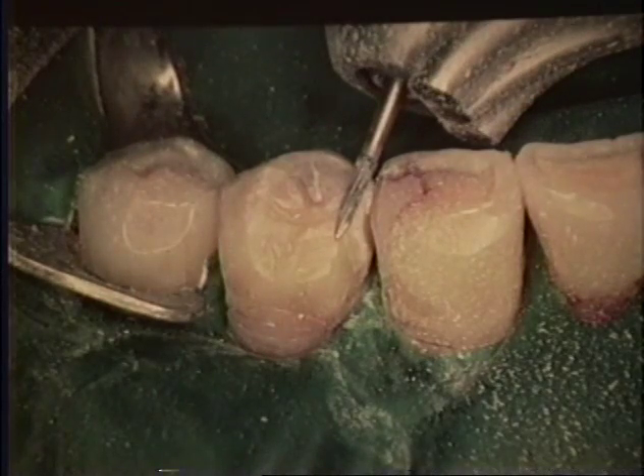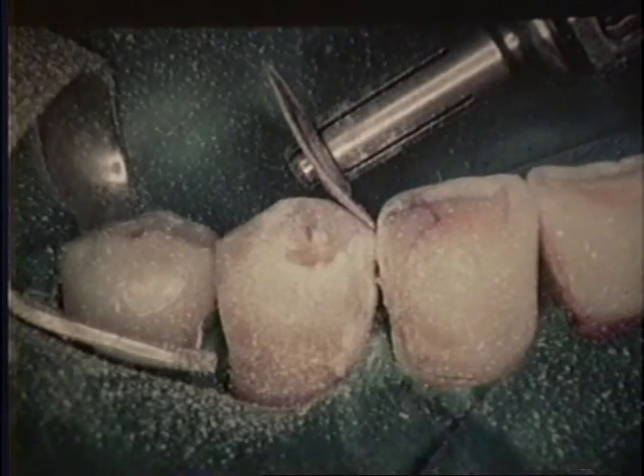And then on the occlusal, a strong advantage of Helio is that you can polish it quite acceptably with a 12-bladed sharp carbide, preferably brand new. Now Herculite and some of the others unfortunately don't cut very well with a 12 blade. Then you disc as appropriate, disc it out and get good contour.